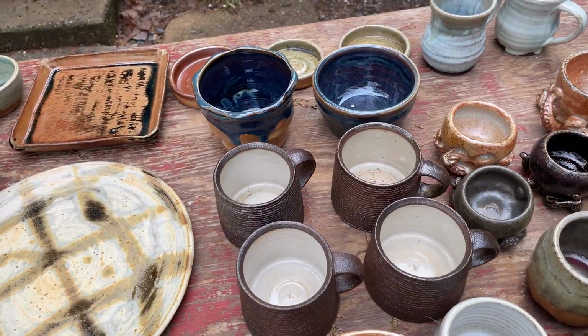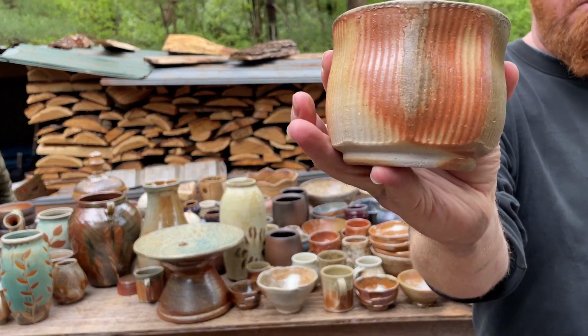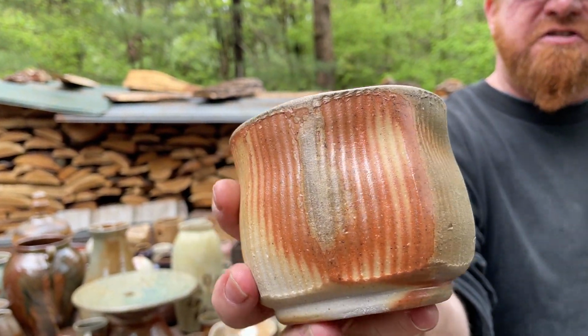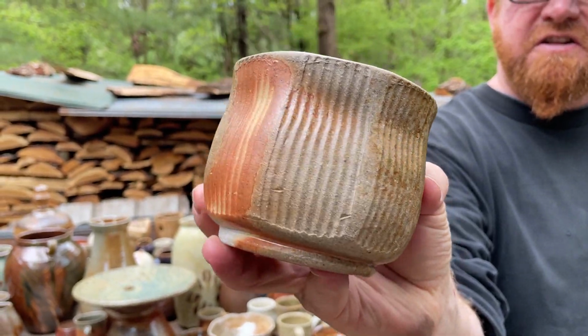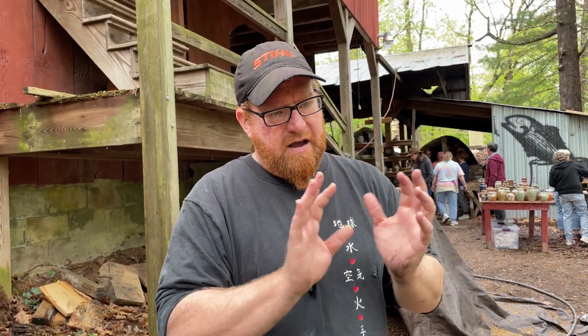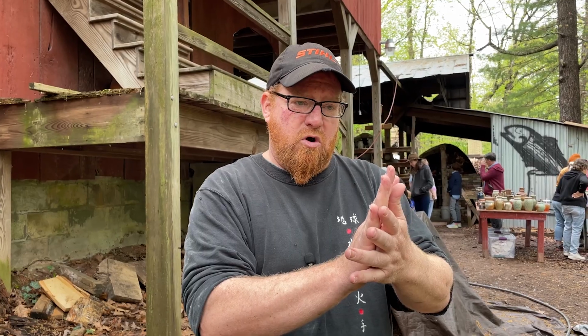Flashing is another factor that's in the wood. There's salt, potassium, stuff like that in the wood vaporizing above cone 6, and that's giving a flashing effect, which is usually orange to brown type of colors that move from the windward to the leeward side of the pots. One side gets hit more, and then the other side might be lighter. That's the effect of the minerals in the wood vaporizing in the fire and then interacting with the clay.